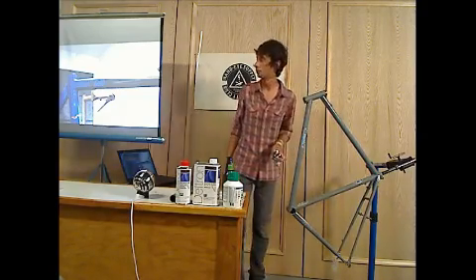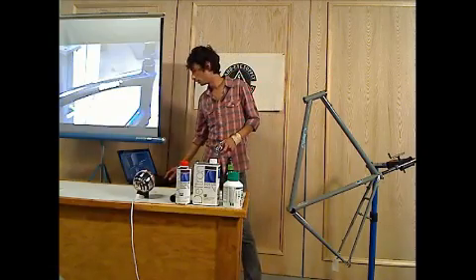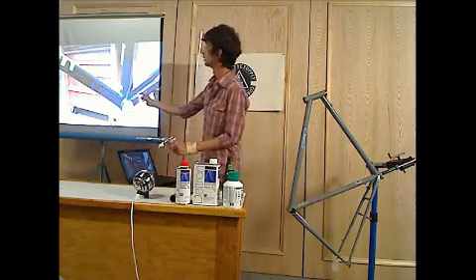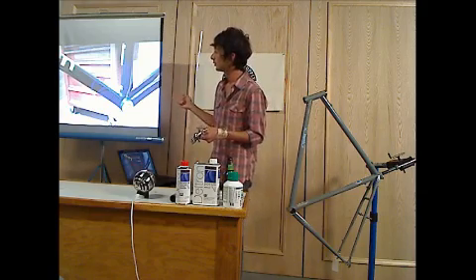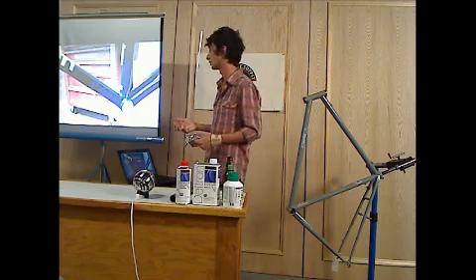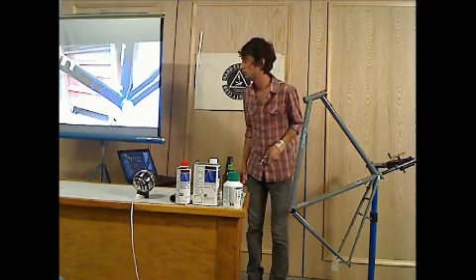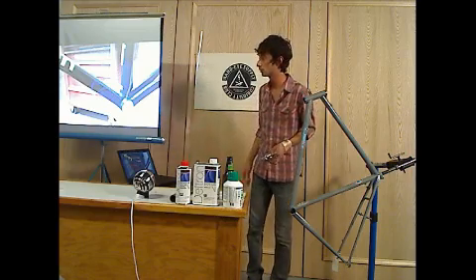So back to clear. For carbon fiber, you would use a different kind of clear, because carbon tends to bend a lot, especially these joints. That's just another example of how carbon's very different. It has a lot of flex in it. So you want to use a clear with some kind of flexible agent in it, basically. A good comparison is Shimano fishing poles. They use that kind of stuff because you need that flex, and it's pretty much the same stuff used for that.